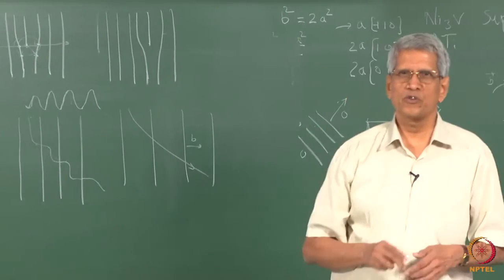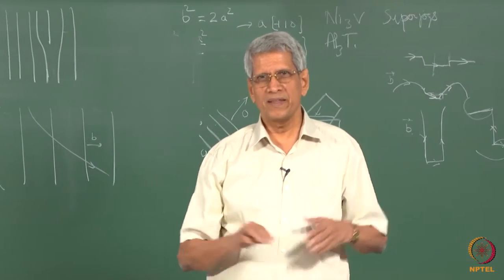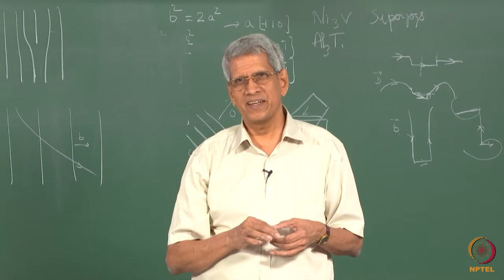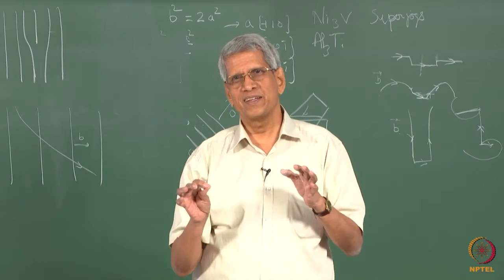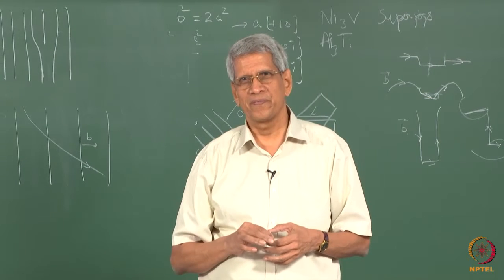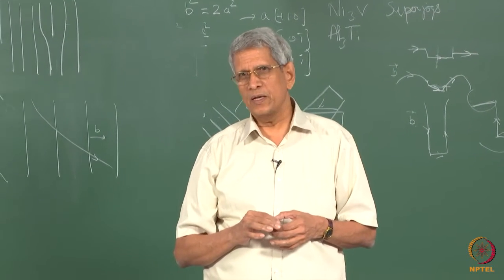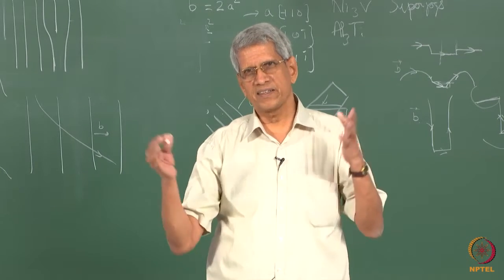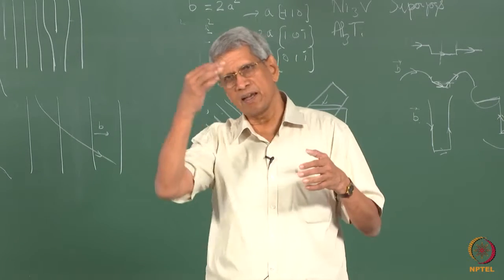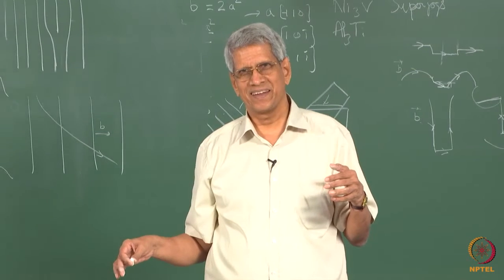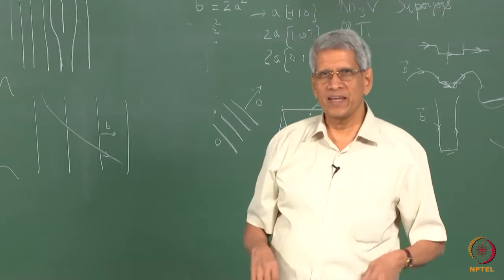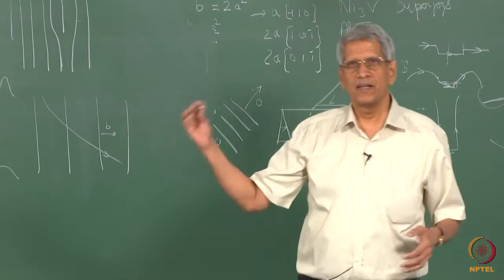So this way also kinks could be created, because the dislocation line would try to remain in a position where overall it is in a low energy position. This can be prominently seen in many ordered alloys, where the long lengths of the dislocation line will be seen either as an edge or a screw type, or mixed type of lines.